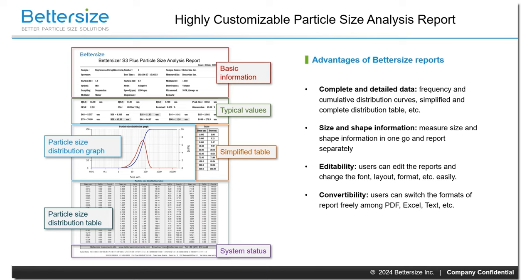The default particle size report generated by Bettersizer S3+ includes first, basic information of sample, like the sample name, operator, and test date. Second, particle size typical values. The number here means particle size in accordance with content percentage, such as D10 of this sample is 11.63 microns, which means 10% of this sample is smaller than 11.63 microns. Also, to present particle size distribution, there is distribution curve, table, and a simplified table.